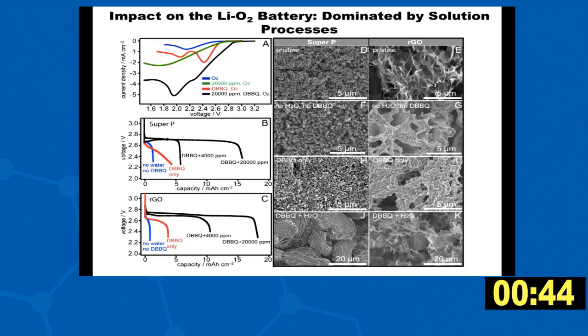If you look at the SEM, here are the two electrodes. In the absence of water and DBBQ, what you can see is the electrodes very quickly get passivated by the lithium peroxide, so the reaction shuts off because you have no more mechanism of getting electrons into the system and reducing the oxygen. You put DBBQ in, and then you can start to promote these solution-based mechanisms, and you can see much bigger particles emerging. And then you put in water, and you get these monstrous particles that are more than 10 microns in size, and you get these beautiful toroidal structures and a significant increase in capacity.